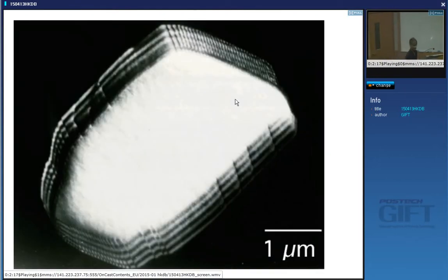And this is an image of boundary around a bit of austenite in ferrite, and you can see arrays of dislocations. So physically, this is the real model for the structure of an interface. The spacing will change according to the plane of the interface and so on, but you will clearly be able to image these dislocations when you look at them in a transmission electron microscope. Yeah? So the structure of a boundary can be thought of in terms of dislocations with specific Burgers vectors and so on. And here I mentioned a tilt boundary where I cut the crystal and then I bend, tilt. But you could also have a twist boundary where I cut in this plane and then I twist like this. So there you would have some screw dislocations to accommodate the difference.